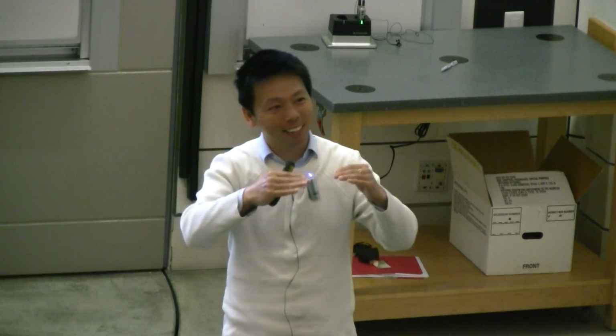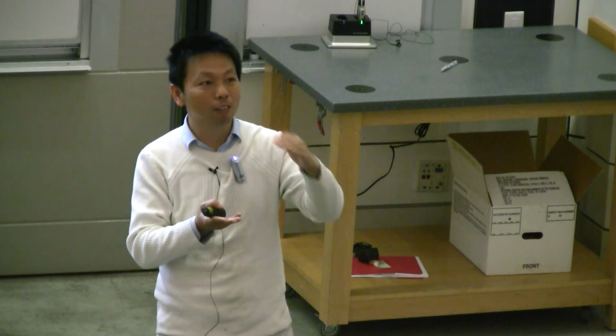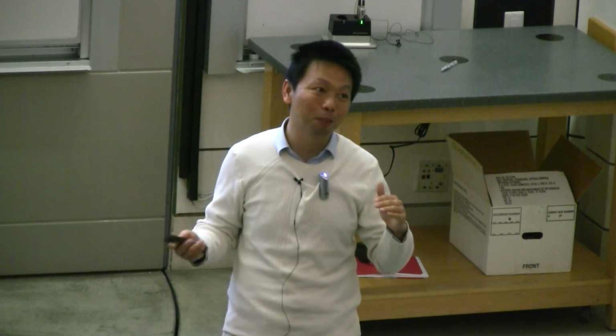We do make electrical contact, but in electrical transport measurement, the contact has two roles. One is it can serve as a contact to gate the sample. In that case, even a very bad contact works fine, because the leak current is very, very small. Even if you have a contact with megaohm or tens of megaohm, you can still use it to gate the sample, and that's what we are using it for here. So you can still gate it to inject electrons and inject holes. But if you want to use those contacts to measure electrical transport, say resistance and mobility and so forth, you want the contact resistance to be in the kiloohm range, and that is very hard. So we can make a bad contact that's sufficient for gating, but we cannot make a good enough contact to do nice electrical measurements.